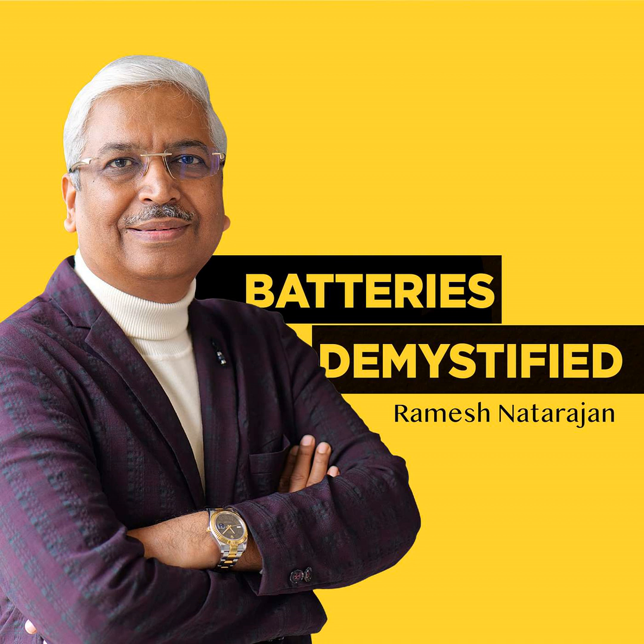Now, you also make for lithium ion, right? Correct. Yes. We've just launched a product called Vanisperse LI, which works by dispersing carbon and graphite in lithium ion battery slurries. What that does is several favorable things for lithium ion electrodes. First, it prevents agglomeration of carbon and graphite particles, which gives you a more stable and smooth cast surface. The other thing that it does is it prevents this phenomenon called particle jamming, where you're trying to put different sized particles through your slot die coater too quickly. And particle jamming results in bubble formation and poor adhesion to the electrode and an uneven surface.